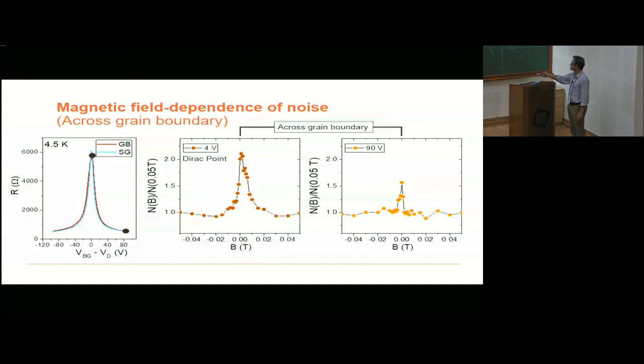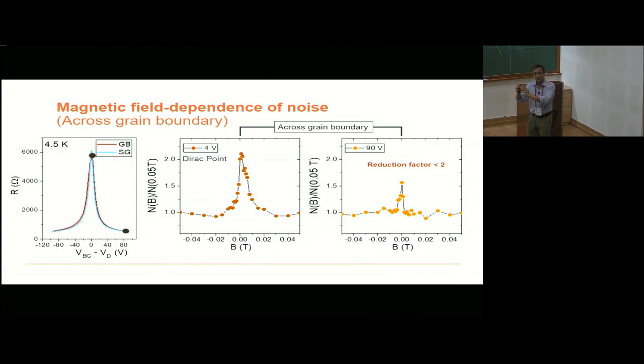And this essentially is the reduction factor. It means that now the noise is no longer entirely dominated, the absence of time reversal symmetry is no longer due to the magnetic field anymore. It has already been removed partially, because it has not gone to 2, but it has gone to 1.5. I'm going to show you more data here. The time reversal symmetry probably was partially removed already from the system, and hence the magnetic field has reduced only a fraction and not entirely from 2 to 1.